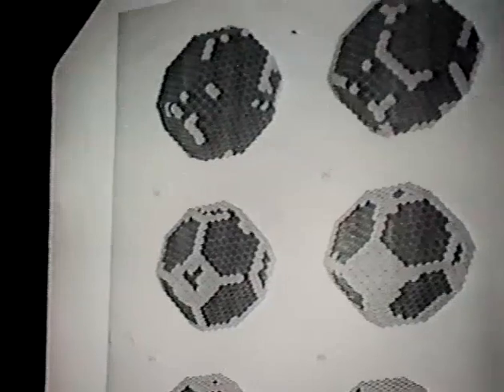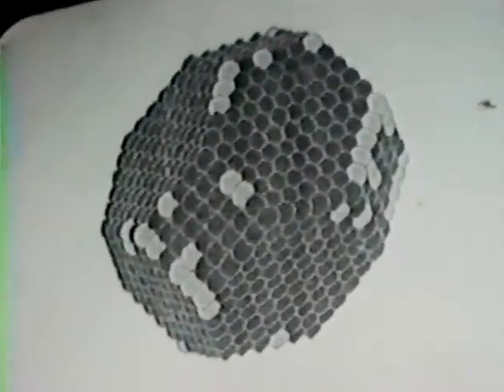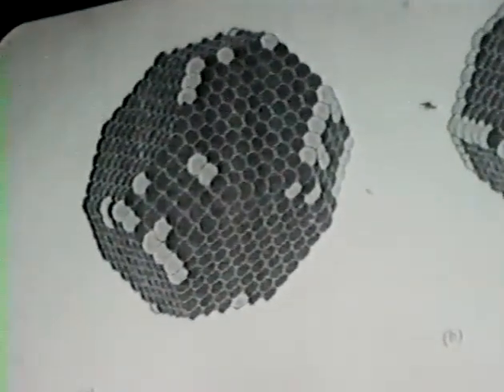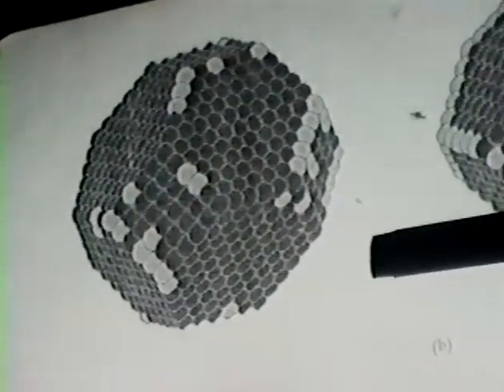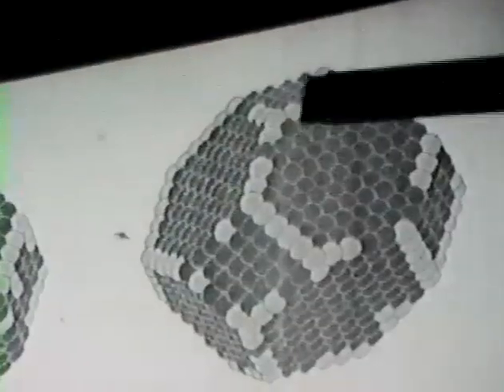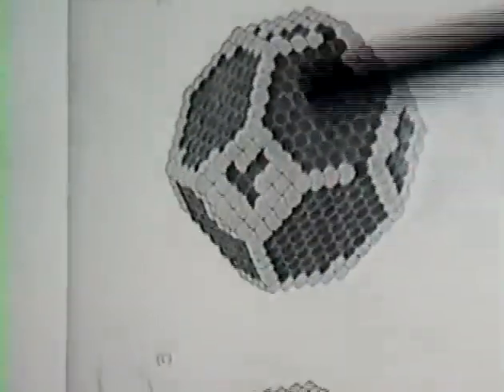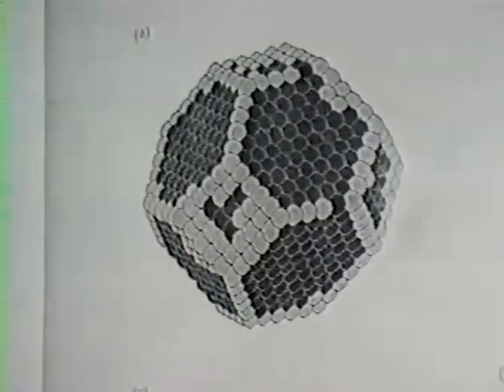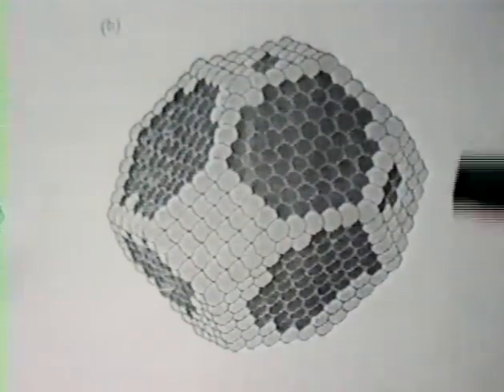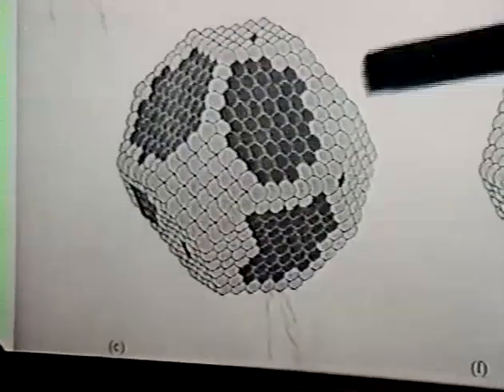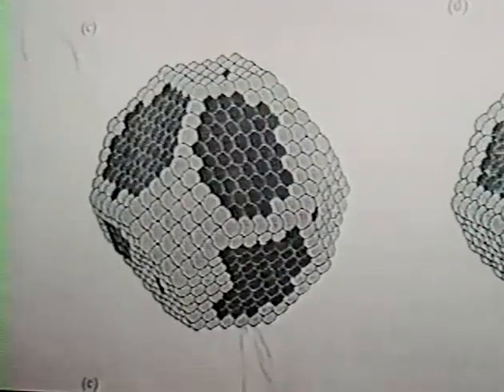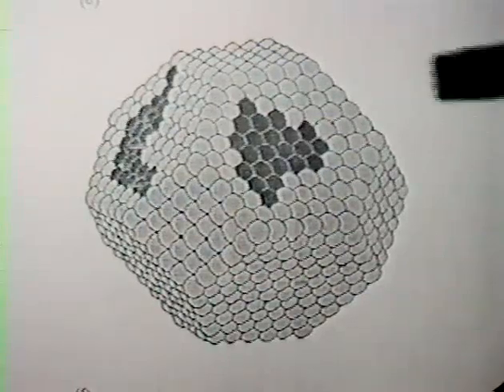Looking at Monte Carlo simulations, we consider varying amounts of copper, where copper atoms tend to go to low-coordination sites — edges, corners, and so on. At roughly 2% copper, these edge and corner sites begin to be populated; at about 5% copper, we're populating almost exclusively those sites; at 10% copper we've pretty much filled those low-coordination sites. At 15% copper, we've lost all edges and corners and are now covering the low-index planes. Importantly, even at 20-30% copper, you never get to the point of making small ensembles of ruthenium — large ruthenium ensembles persist.